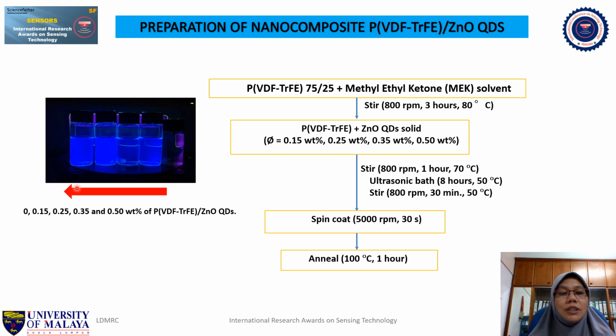So this picture here shows the color that has been produced by the zinc oxide quantum dot that we have synthesized, at various weight percentage concentrations of zinc oxide inside the PVDF-TrFE polymer host. So you can see from clear to blue color emission.